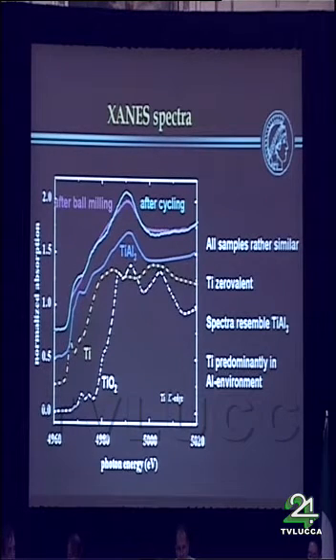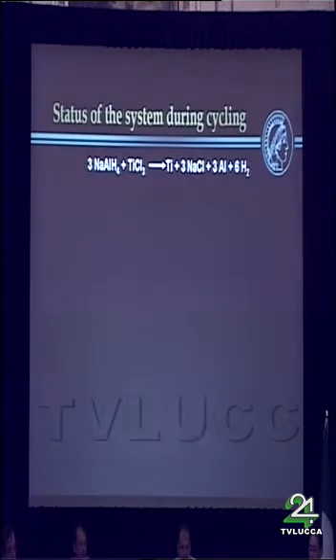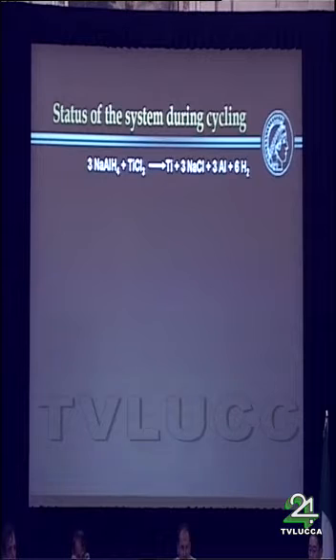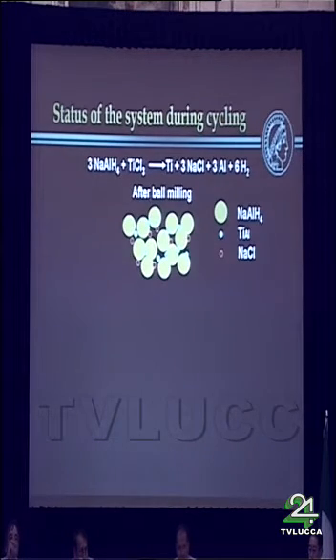It's certainly not titanium metal. It's certainly not an oxidic compound. There is some probably disordered state of the titanium surrounded by aluminum neighbors. And based on this observation and TEM data and other data, we think what's going on in the system is